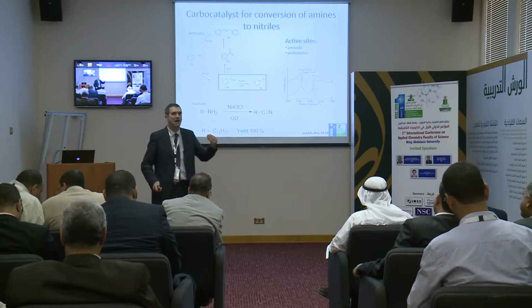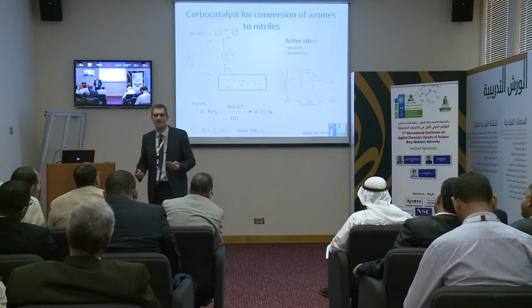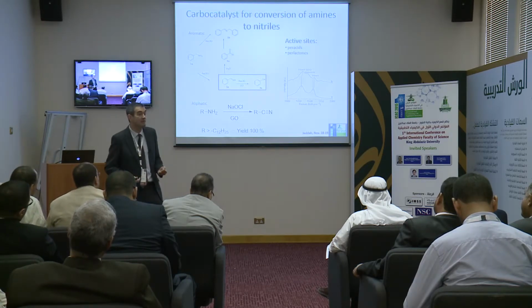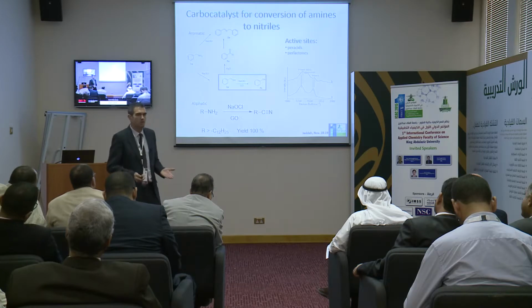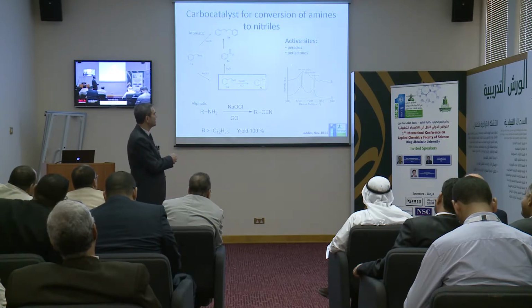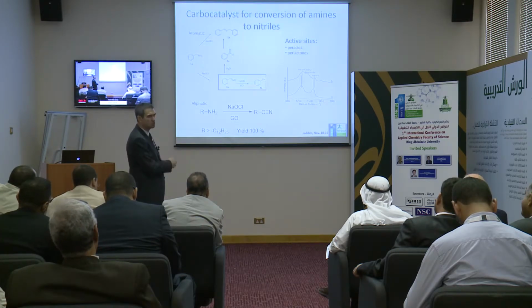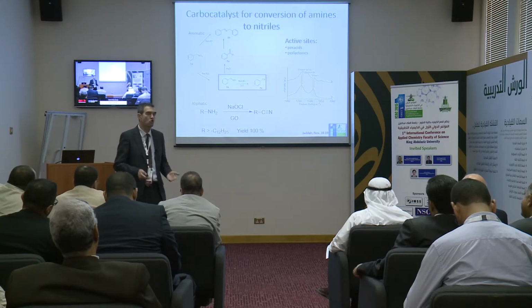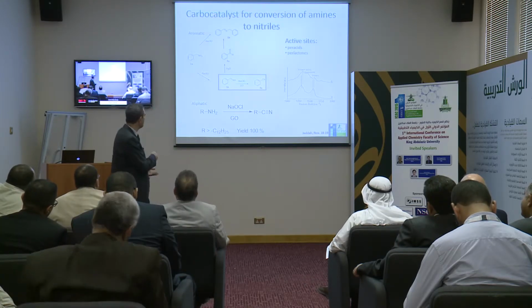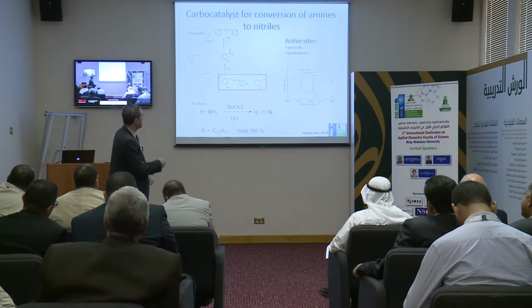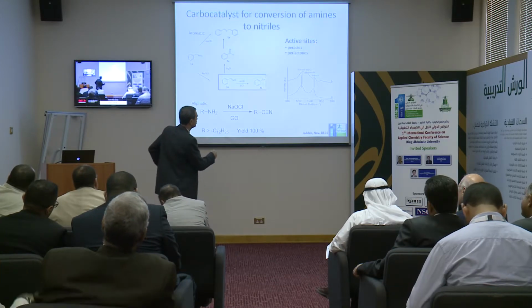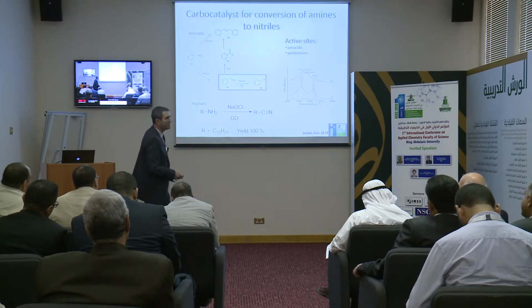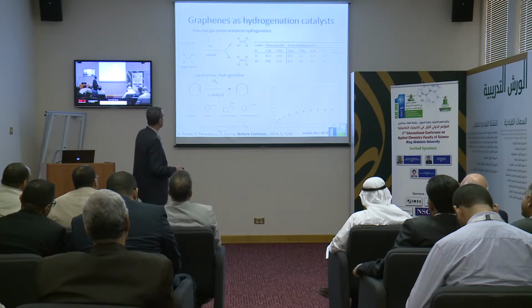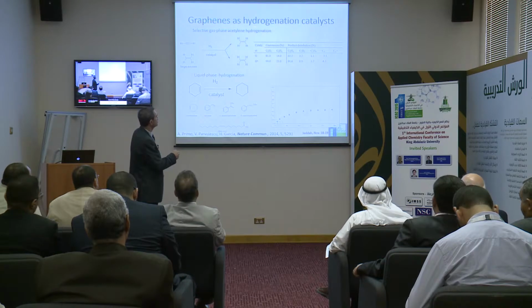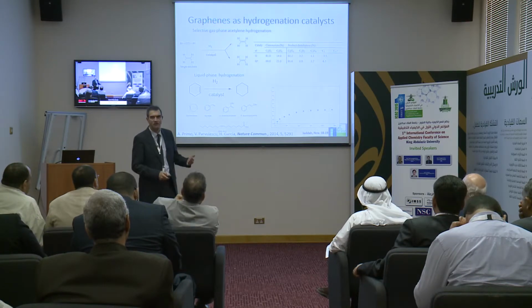Again, coming back to organic chemistry, what is special in the case of graphene? And the answer maybe is nothing, because it was known that if you have an acid and you have an oxidant, then you form the peracid. And it was known that the peracid was able to do this chemistry, oxidations. So really, these are the active sites, and what we need is just a graphene that contains some oxygenated functional groups. Graphenes can also be catalysts for hydrogenation in the absence of any metal.